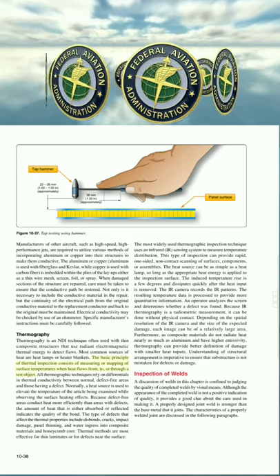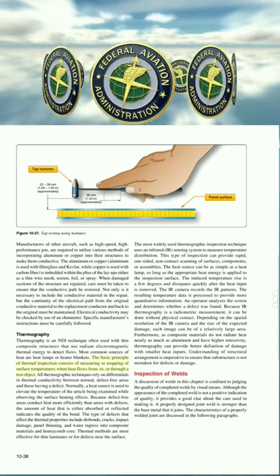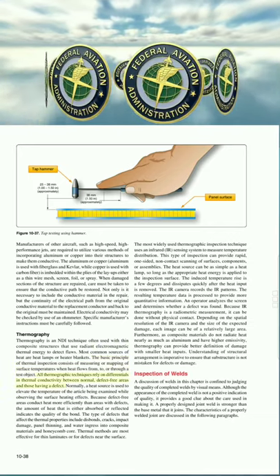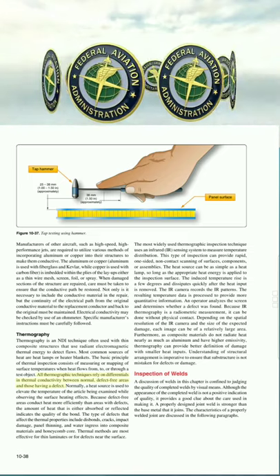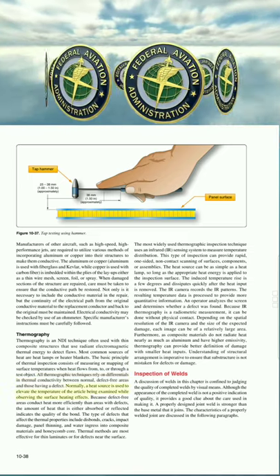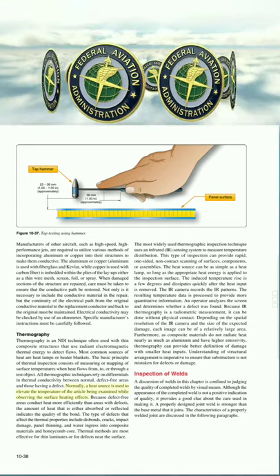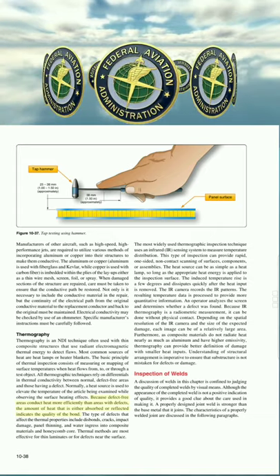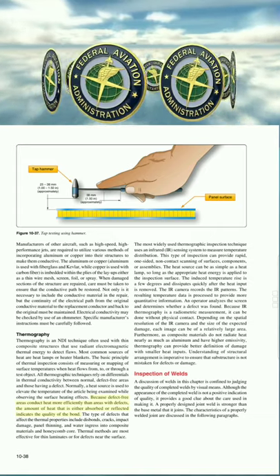The basic principle of thermal inspection consists of measuring or mapping of surface temperatures when heat flows from, to, or through a test object. All thermographic techniques rely on differentials in thermal conductivity between normal, defect-free areas, and those having a defect. Normally, a heat source is used to elevate the temperature of the article being examined while observing the surface heating effects. Because defect-free areas conduct heat more efficiently than areas with defects, the amount of heat that is either absorbed or reflected indicates the quality of the bond.